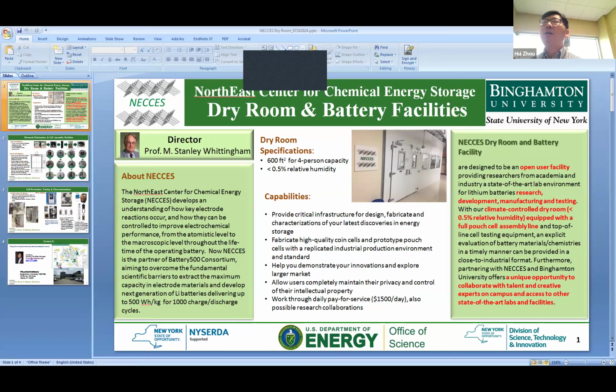So for pouch cells, we have the double cup formation machine, which can give us a stacking thickness of up to 13 to 14 millimeters. That means we can make a cell with a maximum of about 40 to 50 layers inside the pouch cell. And besides all the cell making facilities, we also can do some cell formation and testing. Presently, we have about 250 cycler channels for the coin cell test. The current can go up to 1 ampere.